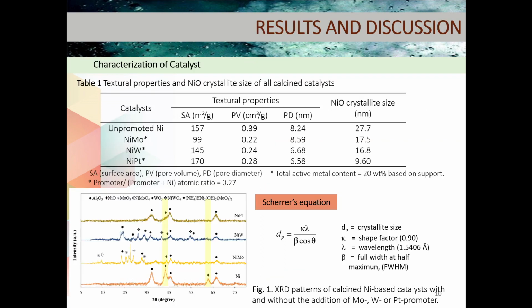And then this slide shows the textural properties of the catalyst and the nickel oxide crystallite size. And you can see that before we add the promoter into the catalyst, it shows a surface area of about 157 square meters per gram. And after we add the molybdenum or the tungsten into the nickel catalyst, the surface area tends to decrease. But it's not so for the nickel platinum. It still shows a high surface area of about 170 square meters per gram.